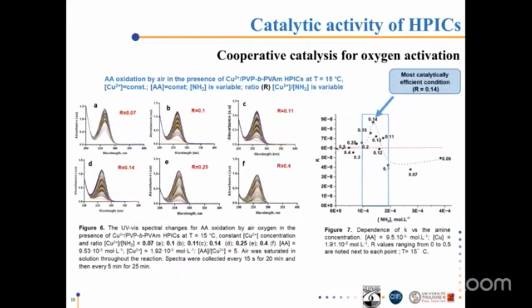In order to answer this question, a series of experiments were conducted at constant concentration of ascorbic acid and copper, but different concentration of polymer. In this experiment, we keep a constant concentration of ascorbic acid and copper ions, but we change the ratio between copper and amine groups inside of the copper polymer mixture. Corresponding rate constants were estimated and plotted as a function of amine concentration, figure 7.